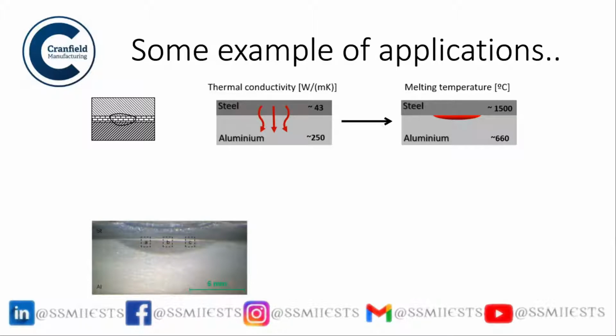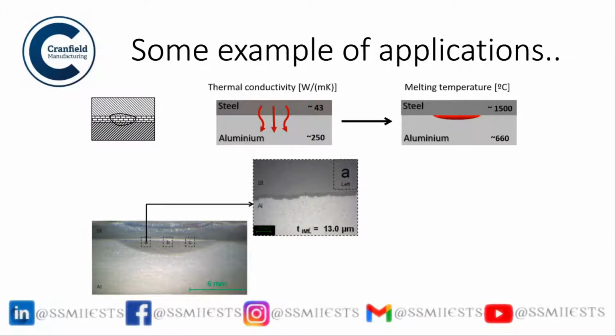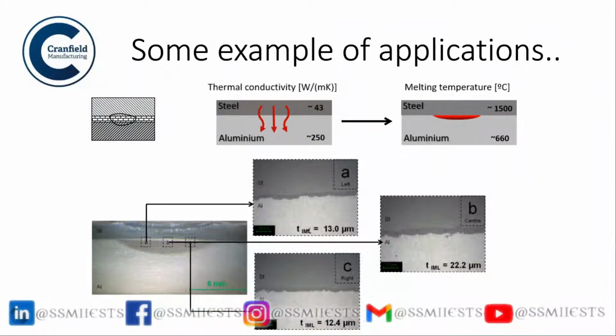However, you can see here, this is the actual macro of that, and here at the top, it is molten. The steel is about 2 millimeter thick. Now you can see here this molten steel at the top, so you really can create a gradient where at the interface aluminium will be molten, which basically means 660 degrees centigrade for pure aluminium. But for aluminium alloys it might be 550 and so on. And here is steel, which is roughly 1470, 80 like that. So you can create a kind of thermal gradient that will allow aluminium to melt at the interface and wet the steel. And based on that, you can then study the intermetallic formation in the different parts.